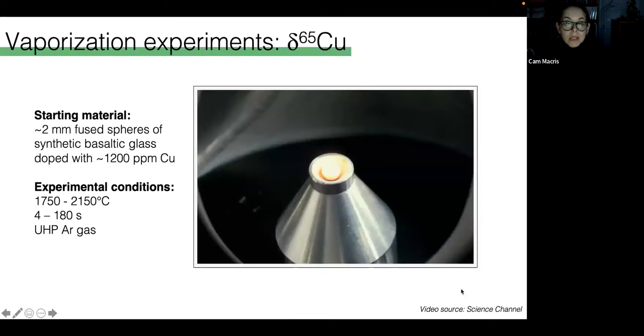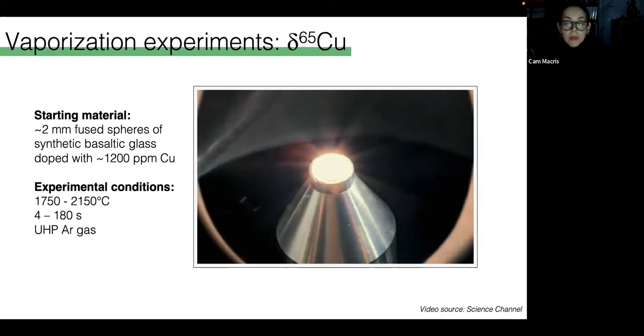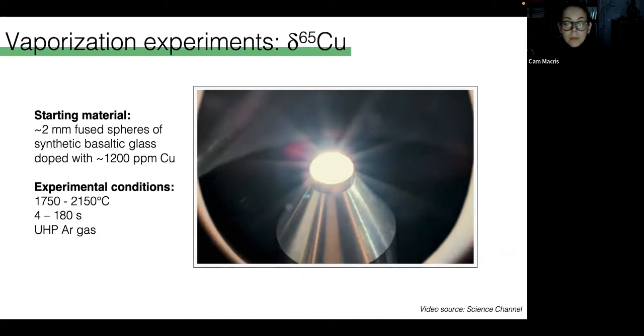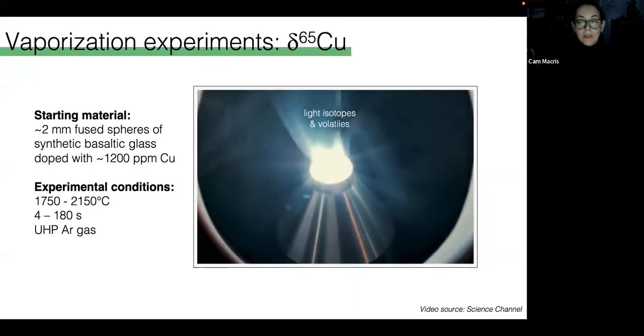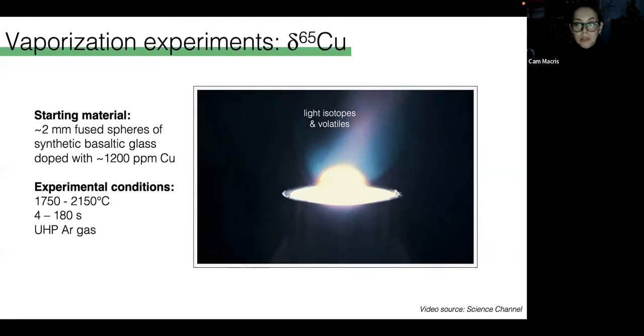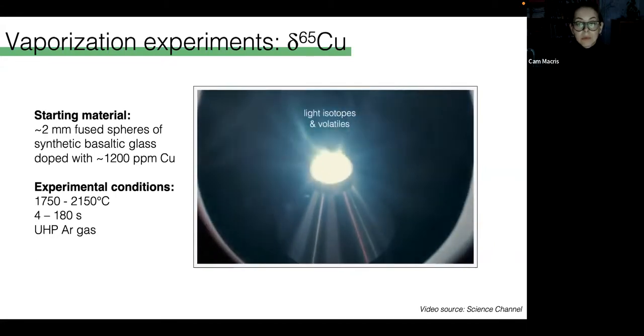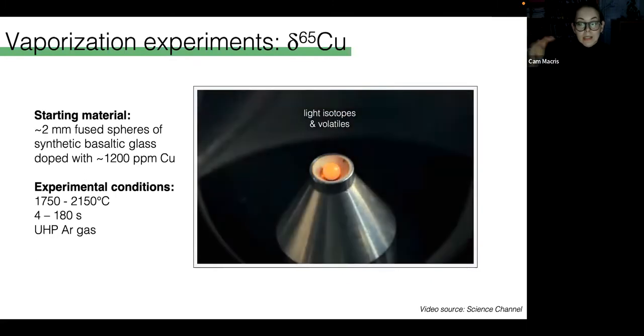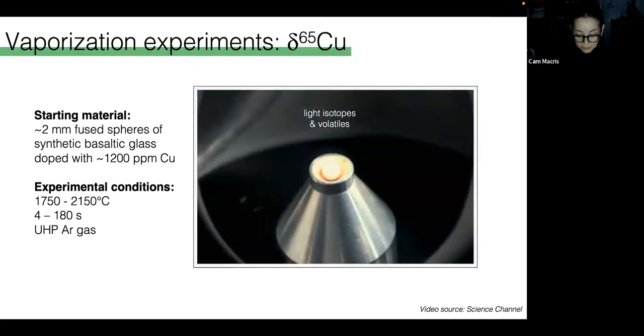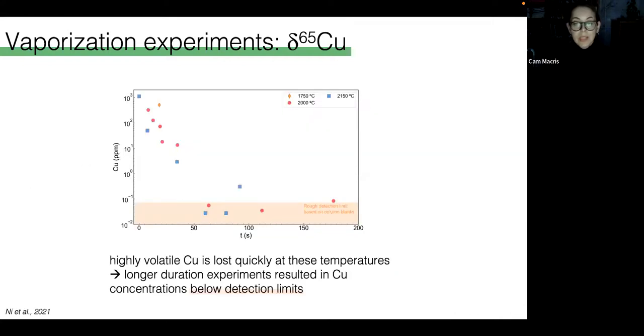So much like the first study I presented, I wanted to try and see what conditions could replicate the observations from the natural samples. So we did vaporization experiments using a synthetic basalt glass doped with extra copper as the starting material and heated these spheres in the levitation furnace for seconds to minutes at high temperature using argon gas. The video shows the melt being partially vaporized, which results in light isotopes and volatiles being preferentially lost to the vapor. And now let's look at the results of these experiments.